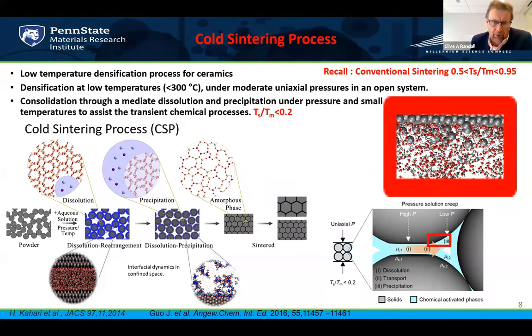from that powder compact. And it allows the sintering temperature to be as low as 0.2 of the melting temperature, which means we can even sinter barium titanate, which is normally sintered at say 1300 degrees, at about 150, just above the Curie point. So it's absolutely a shocking result to be able to do this.